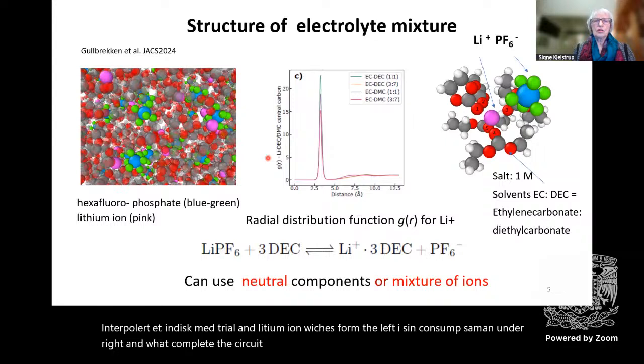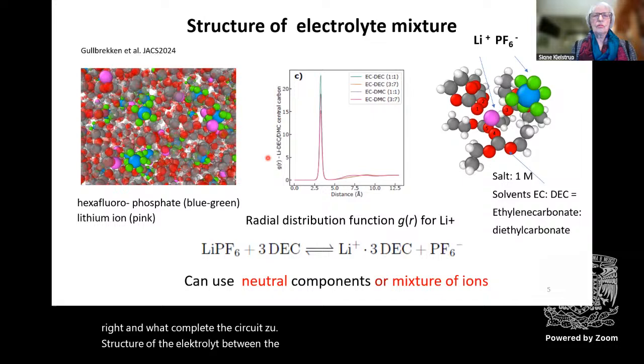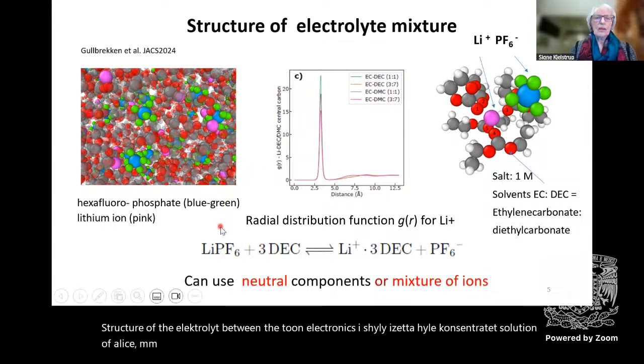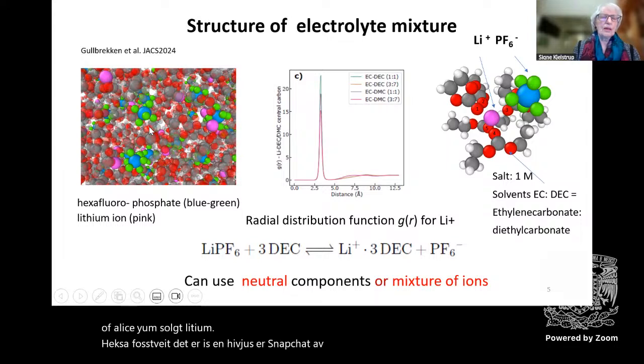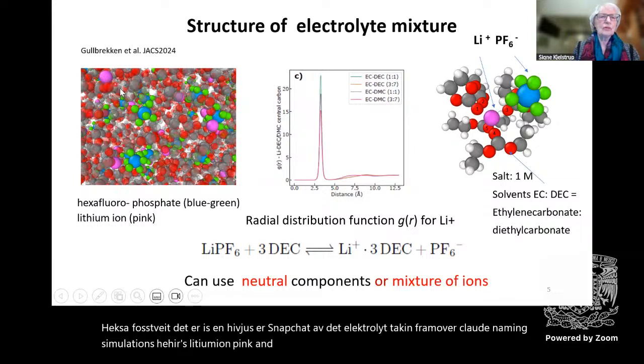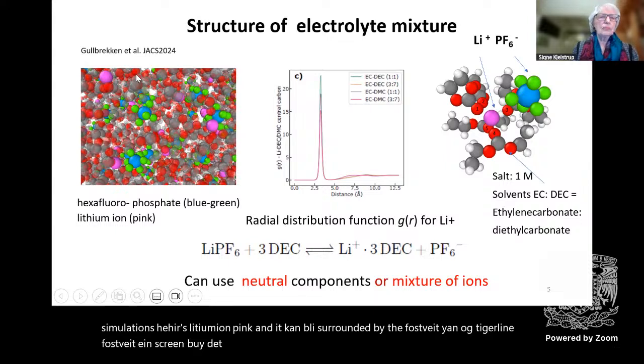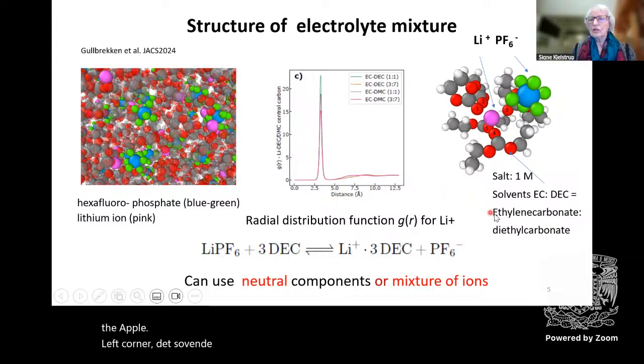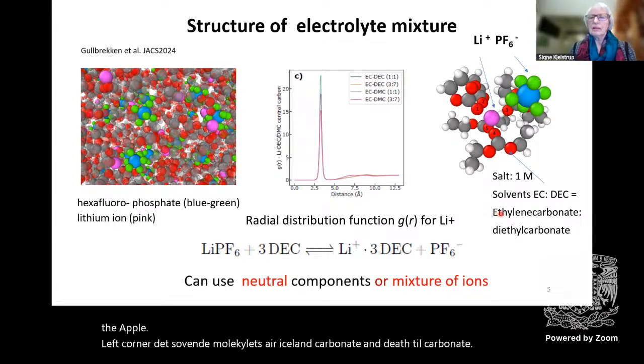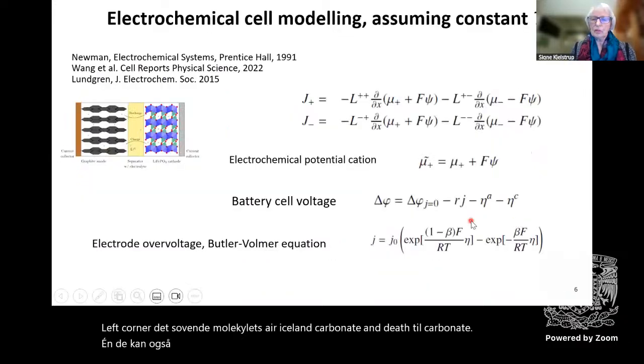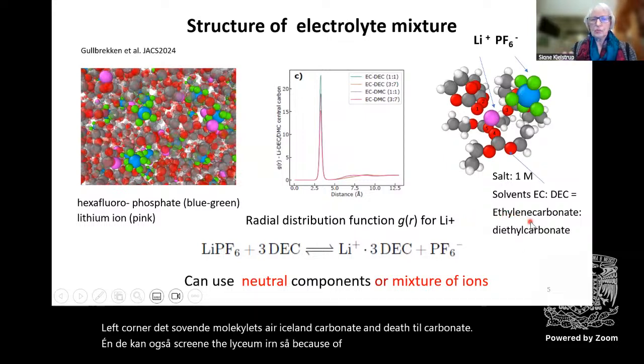So the structure of the electrolyte between the two electrodes is a highly concentrated solution of a lithium salt, lithium hexafluorophosphate, that is. And here you see a snapshot of the electrolyte taken from molecular dynamics simulations. Here is the lithium ion, pink, and it can be surrounded by the phosphate ion, or together with the phosphate ion, screened by the negative ion. But it can also be screened by the solvent molecules, like in the upper left corner. The solvent molecules are ethylene carbonate and diethyl carbonate, and they can also screen the lithium ion, because the carbonate group is also negatively charged.